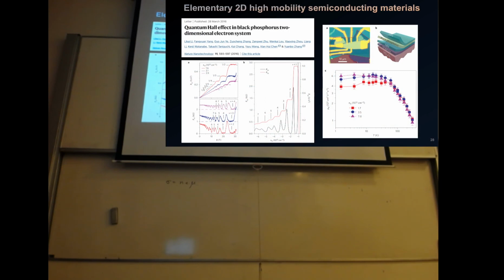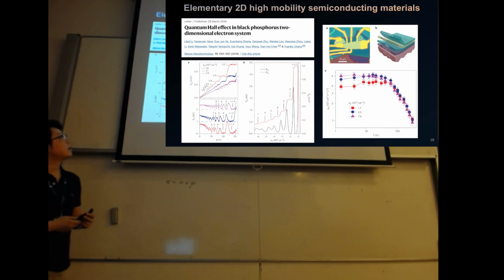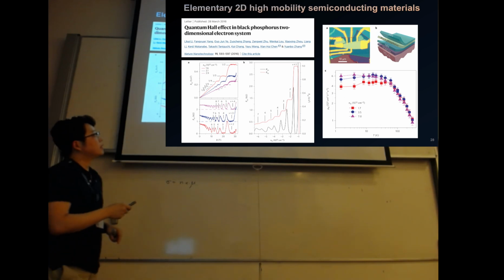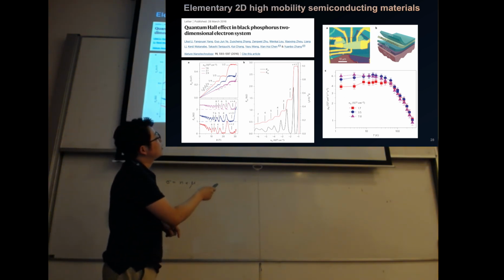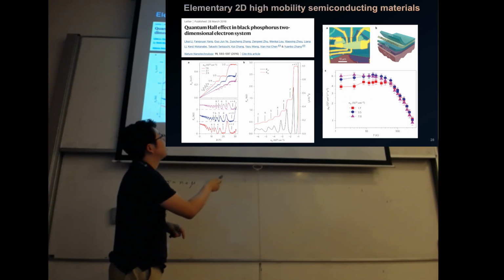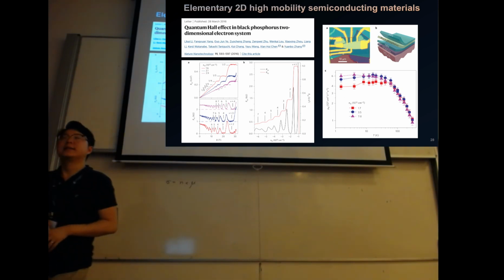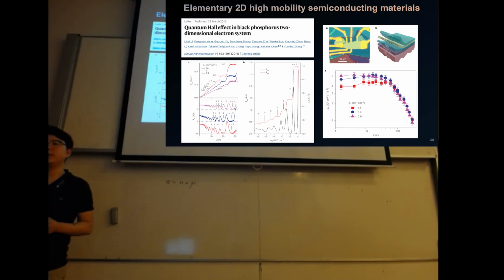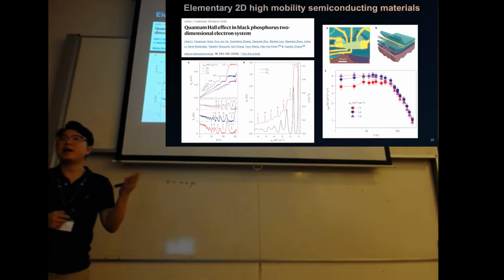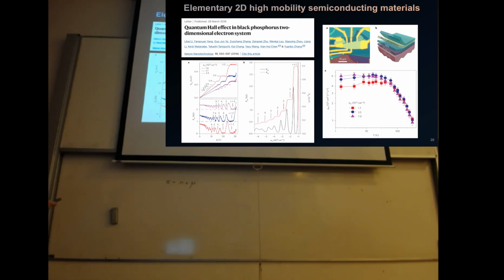Experimentally, people started exploring these two columns of materials, and the first one they found was black phosphorus. This thin layer of phosphorus can show phonon-limited transport, where the mobility saturates below about 30 Kelvin, and you have 4,000 to 5,000 centimeter squared per volt per second mobility. This is high enough, because a few thousand is good enough for us to see quantum oscillations and quantum Hall states. This was published in 2016, the first elementary two-dimensional high mobility semiconductor.